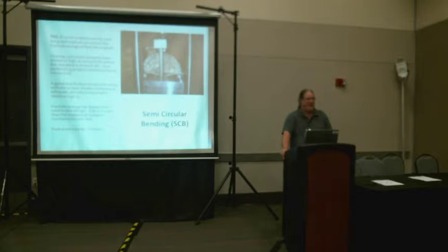Tested Monticello at 0.82. Very, very good number for a CIR and better than most HMAs. So we know that the fracture properties of the material can be built with a very high fracture energy. We know that the properties of the material, it can be built with a very good rutting value.